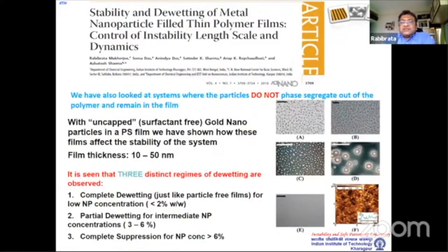So even we did some work with this. In fact, this was my last work at IIT Kanpur before I left, with Satinder, another good friend of all of us, where we could show that we could take some particles which do not preferentially phase segregate, and there is some sort of a virtual cross-linking around these particles within the polymer matrix, and there is a rheology-mediated stabilization also. This is not the most common mechanism. There can be other mechanisms. And Manish will remember that was the time when we had our micro Raman installed. So this was a very fancy measurement that Satinder did for me, where, based on the micro Raman signal embedded on the atomic force microscope, we could pick up or identify the localization of the particles around growing holes. So this is not what I'm going to talk about. This is already a 10-year-old work.